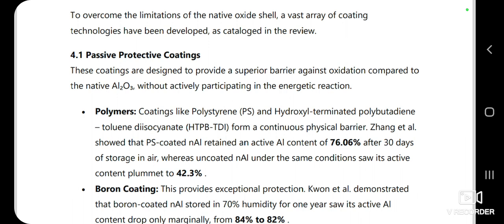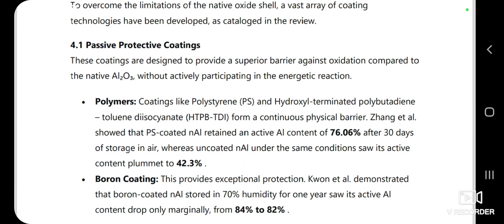Polymer coatings like polystyrene, a thermoplastic polymer, long chains of styrene units, a synthetic polymer, and hydroxyl terminated polybutadiene toluene diisocyanate form a continuous physical barrier around the nano aluminium, and it shows that polystyrene coated nano aluminium retained an active aluminium content of 76.06% after 30 days of storage in air, whereas uncoated nano aluminium under the same condition saw its active content plummet to 42.3%.